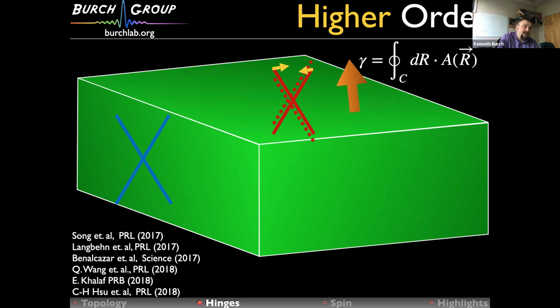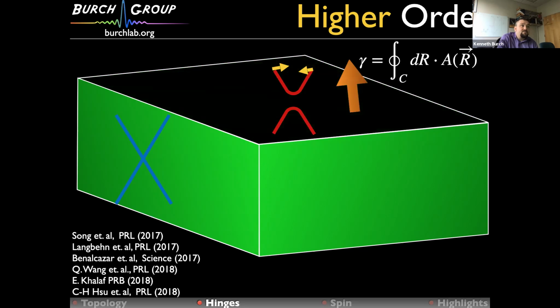However, if I apply the field out of the plane, of course, what happens is then I can mix the states and actually open a gap, right? And so the top surface would disappear. Now, the side surfaces would stay around because, of course, now the magnetic field projects into the direction of the spin for those surfaces, and so they don't get gapped.